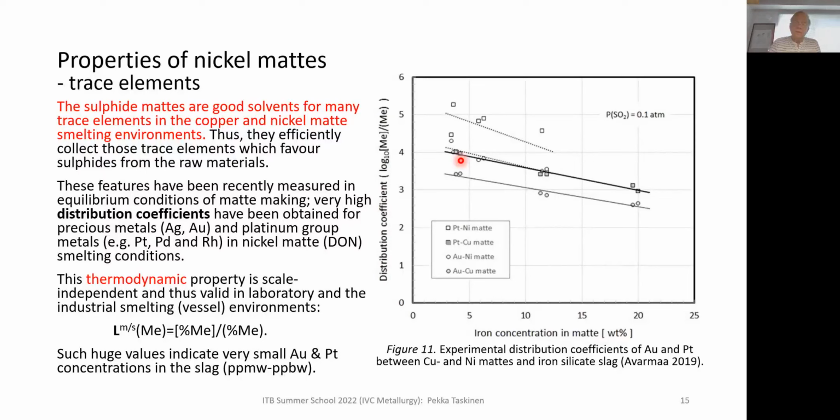So what should we do? The real challenge is to lower the dispersion of matte and improve the settling of this matte dispersion from the slag before discarding it.